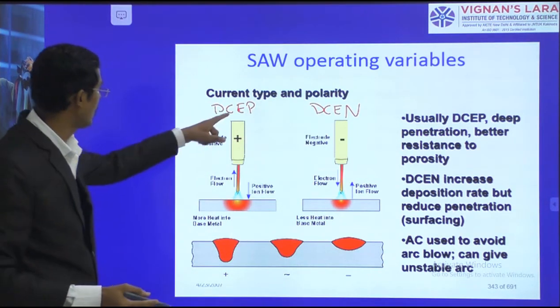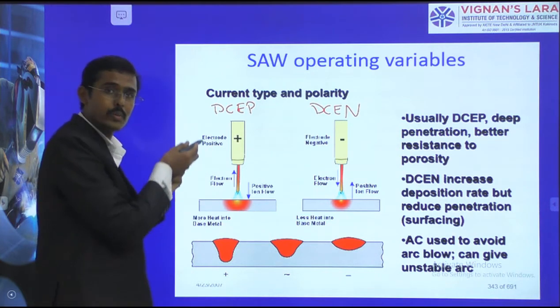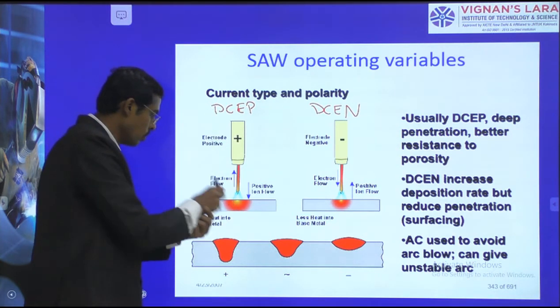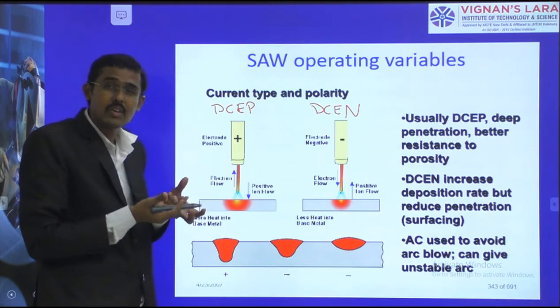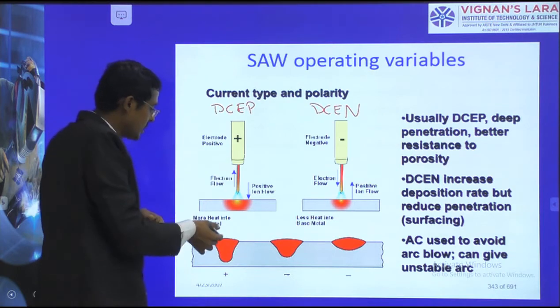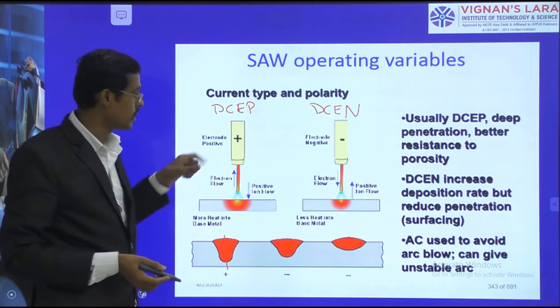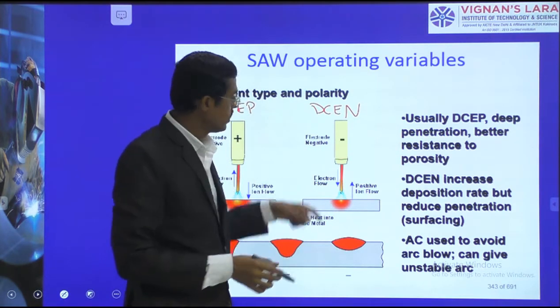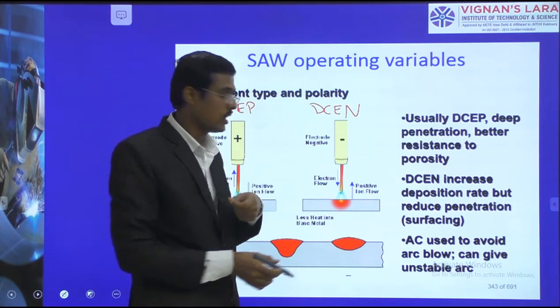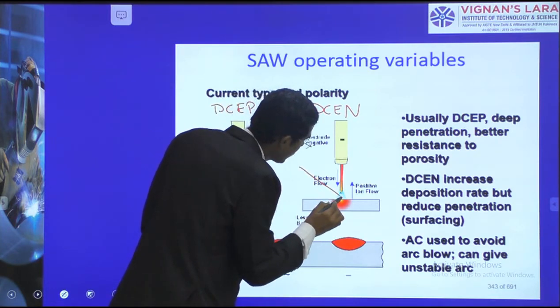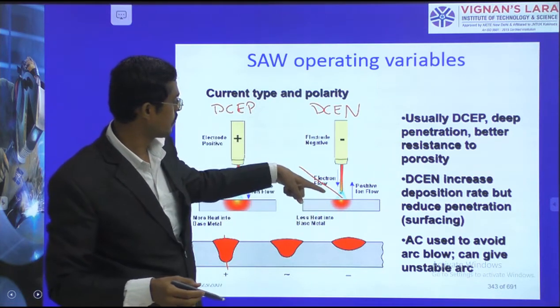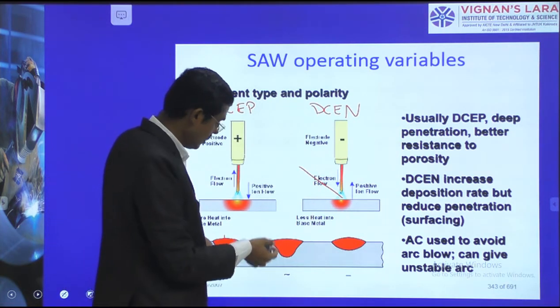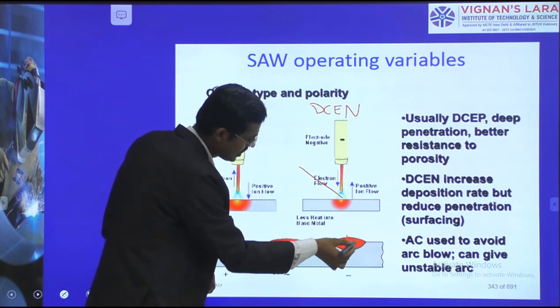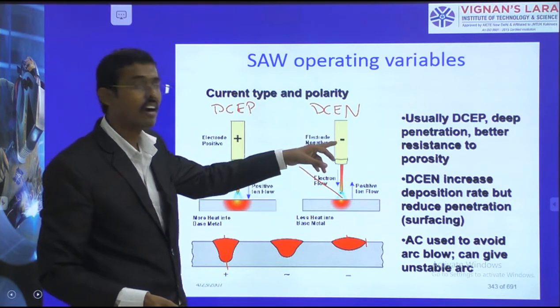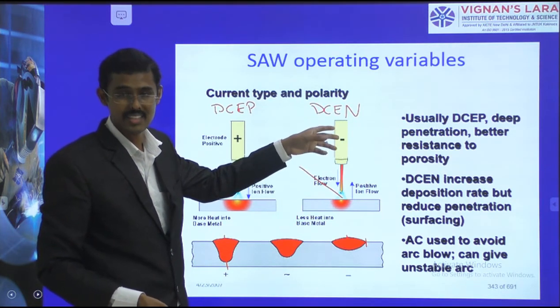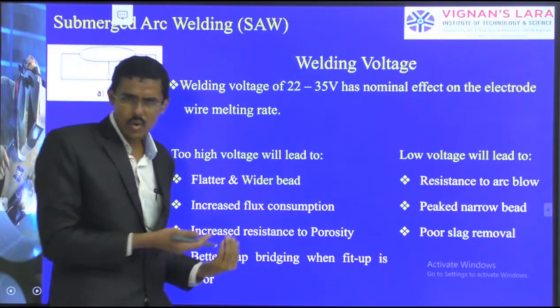In such cases, what happens? In the electrode positive, electrons will go upward to the positive and melt the electrode, which comes down. Therefore, high heat is generated at the electrode because the electrode is to be melted. It is a consumable electrode. After melting, it comes down and generates more penetration, DC EP. But in the similar case of negative, heat is generated in the downward direction. I am supplying one separate consumable electrode wire, like the TIG welding process. The electrode is supplied, heated and melted. So what happens here? Here the penetration is less, but we are able to maintain a non-consumable electrode, maybe tungsten, that we can use here. So welding voltages, now only we have seen.